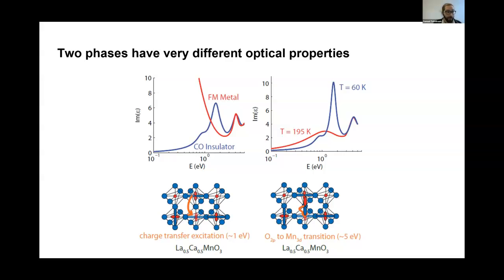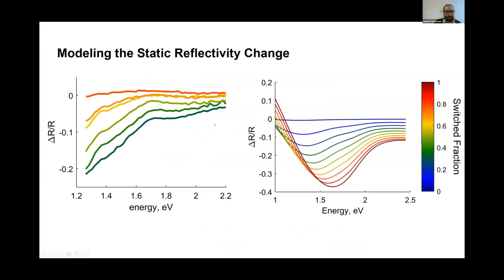And what we're doing with photoexcitation, so this tells us two things. One, what we're doing with photoexcitation is we're exciting a whole bunch of these charge transfer transitions, and we're essentially scrambling the charge order in the system. And this is what allows the ferromagnetism to emerge. The second thing is that the reflectivity in this region, in the visible, is going to be our probe for how much charge order is in the system. And this is what you can see here.